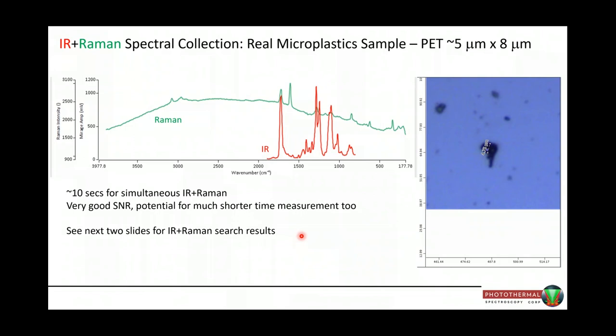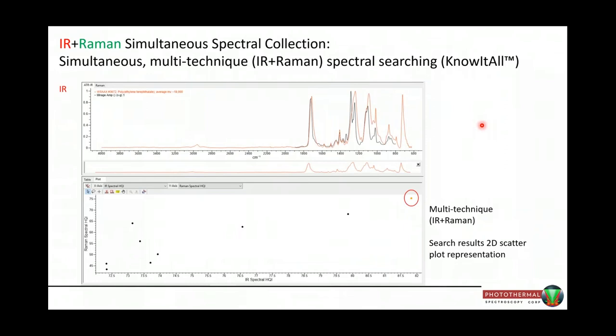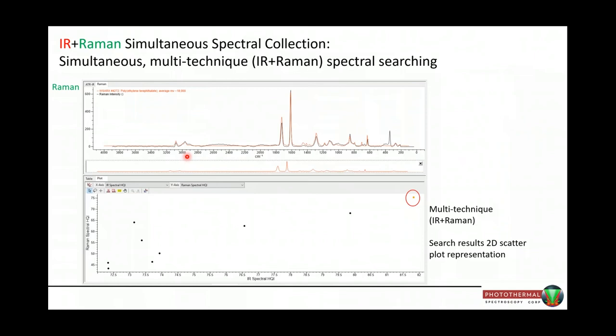And what we can do with the new Wiley KnowItAll search package now is we can do a dual search of these Raman and infrared spectra at the same time, and you get a hit index of the Raman match along the y-axis and a hit index of the infrared match along the x-axis. Here we're seeing the infrared spectrum with the best match, which is polyethylene terephthalate, and the next slide is the same 2D plot, but now we're seeing the match of the Raman spectrum. So sometimes it won't be clear from just one technique which is the best match, but if you have two, you can definitely separate out the best hit from the other possibilities.